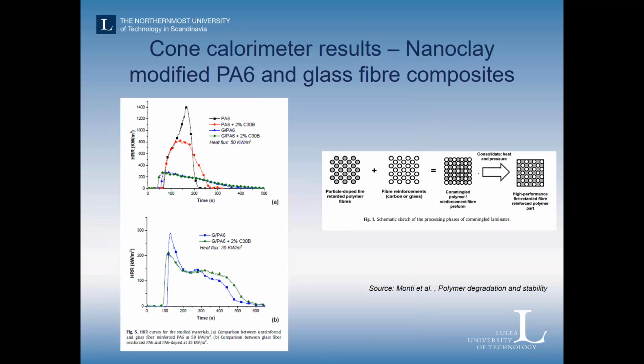And just to illustrate and give some perspective, also presented here are some typical results from polyamide glass fiber composites that one can observe for traditional polymers. So from these experiments, you usually get heat release rate, which is the heat that is generated by the reacting polymer. You start out with an induction time when nothing happens, and then the polymer or sample ignites, and there's a fire, and the heat is generated.